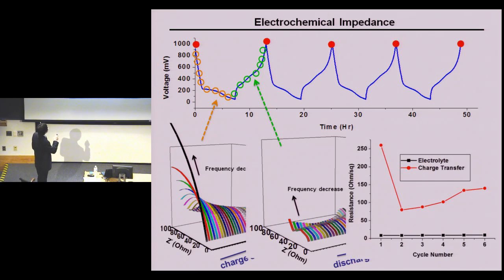And we also measure this kind of semicircle at different charging and discharge states for different cycles. We see here, after the first cycle, the semicircle actually decreases. This is due to the porous structure formation for the silicon structure. And after that, we see the semicircle start to increase. This is most likely due to the SEI layer buildup for this silicon carbon nanotube structure.